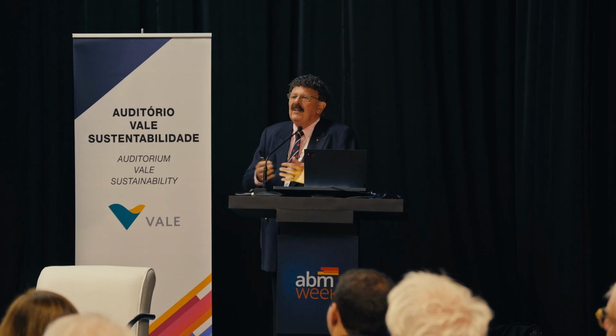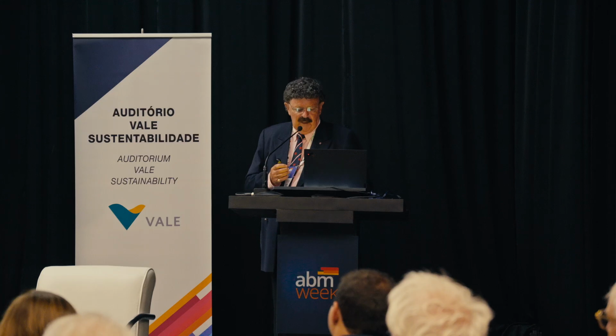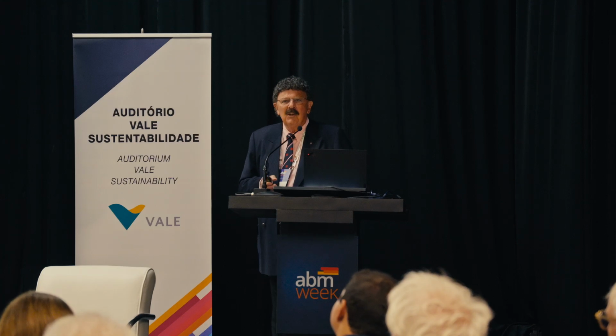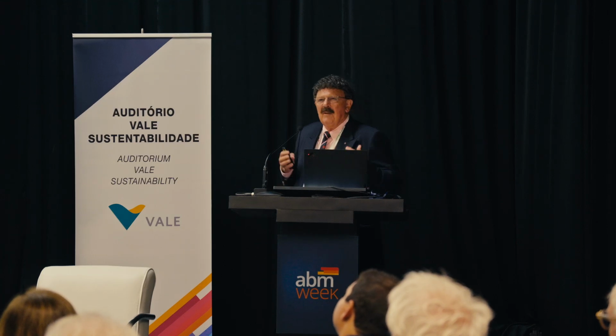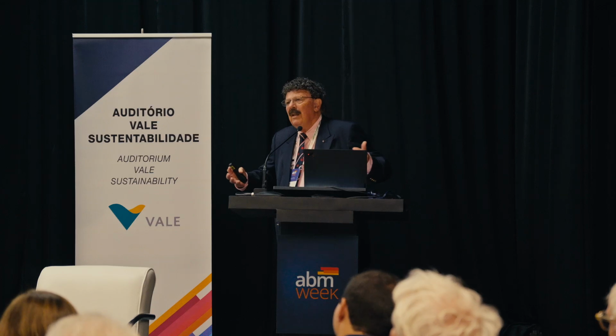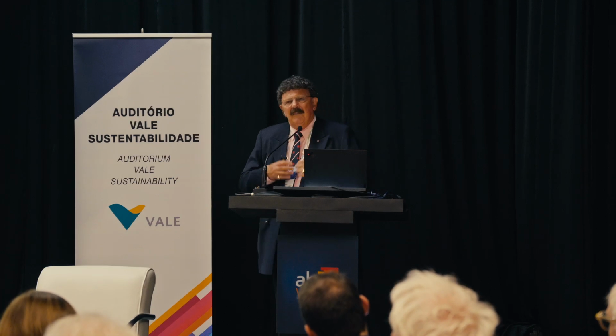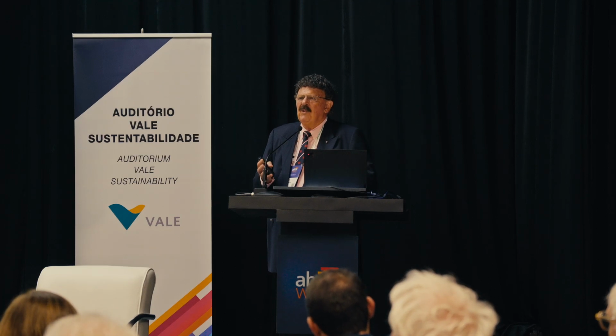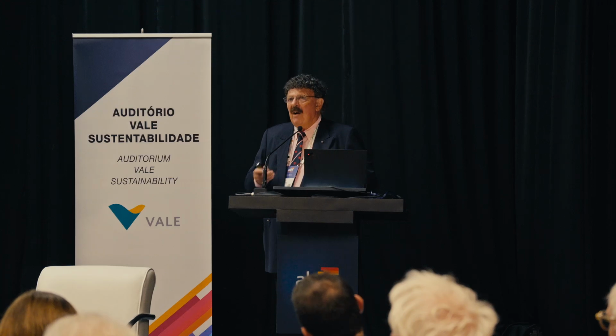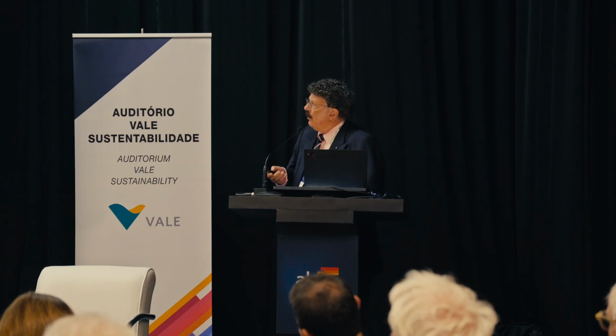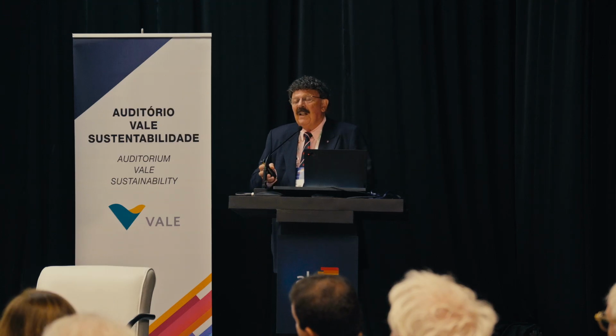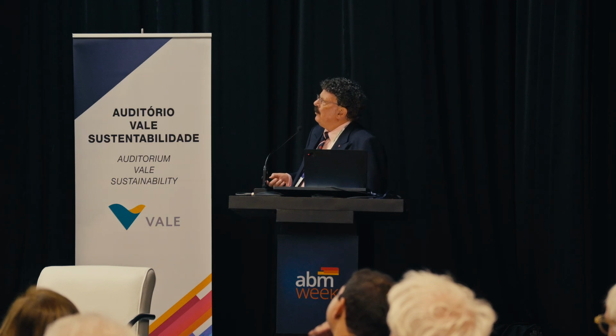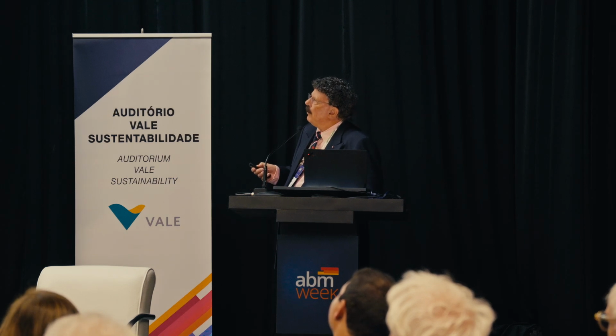So these are interesting differences in the BCC materials. Let me conclude by saying we've looked at these high entropy alloys. They're expensive, they're difficult to process, admittedly, but they have properties which are both unusual and very impressive. The BCC materials show these very high toughnesses, particularly at cryogenic temperatures, particularly at high strain rates, because of this sequence of deformation mechanisms. And we think these materials are probably the toughest on record. We've not seen any tougher.